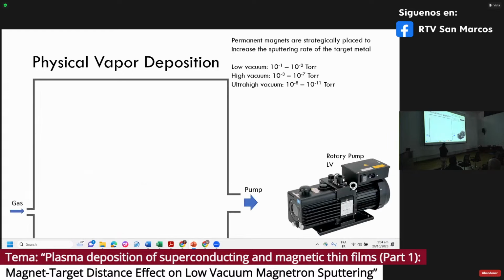Now, moving on, physical vapor deposition is actually a vacuum technique. So permanent magnets are strategically placed to increase the sputtering rate of the target material. But I will talk about that in a short while. So low vacuum, we are talking about 10^-1 to 10^-2 torr. High vacuum is 10^-3 to 10^-7 torr, while ultra high vacuum is from 10^-8 to 10^-11 torr.